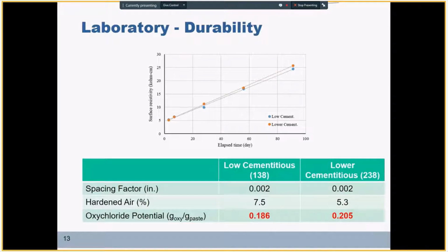A summary of the durability test data: we have the surface resistivity data, very comparable performance for both concrete mixtures, with numbers reaching 25 kilo-ohm per centimeter at 90 days. Very good numbers here, which could also be translated to formation factor and a good index of transport properties for these two mixtures, hopefully suggesting good durability in the long term.